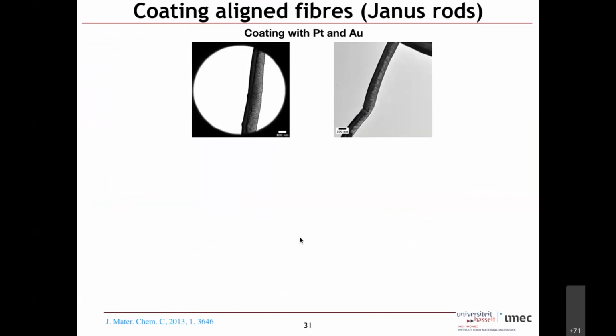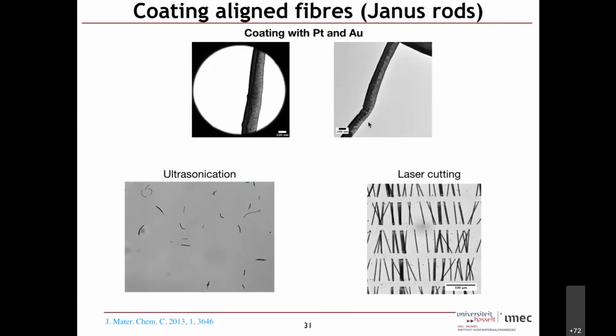Then, once you coat it, you have to see: is the coating good? Is it attached to the polymer or not? This is a transmission electron microscope, where the electrons go in and are transmitted. So you can see that this side is basically platinum, and this side is gold, and this side is platinum, that side is gold. That is how you coat the material, and you can see that it's there.